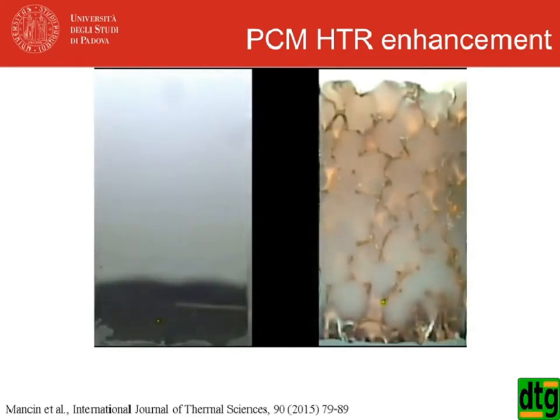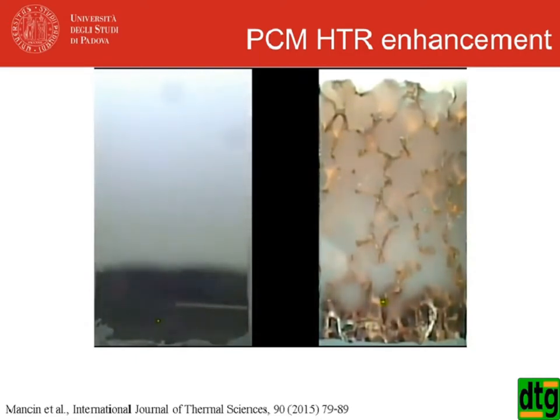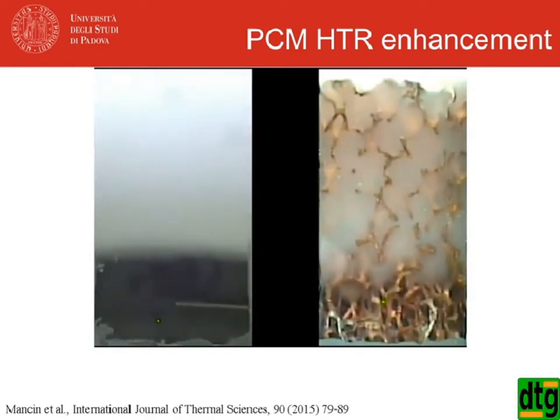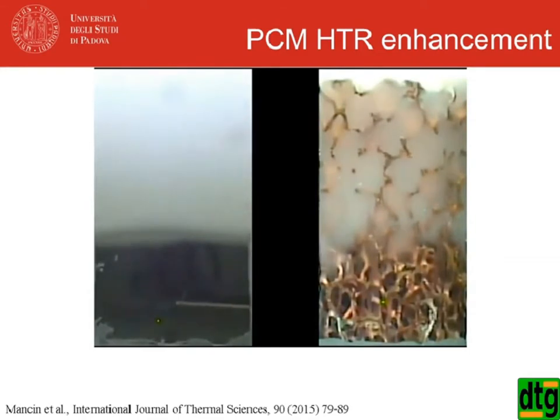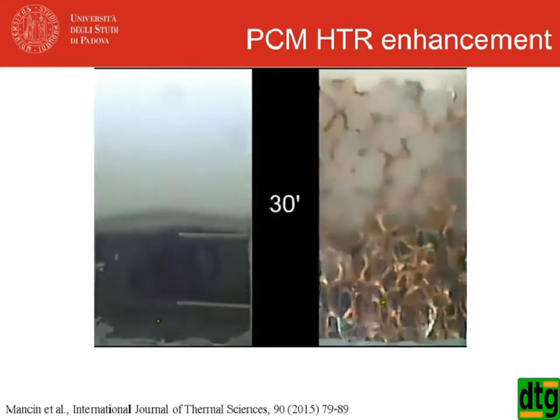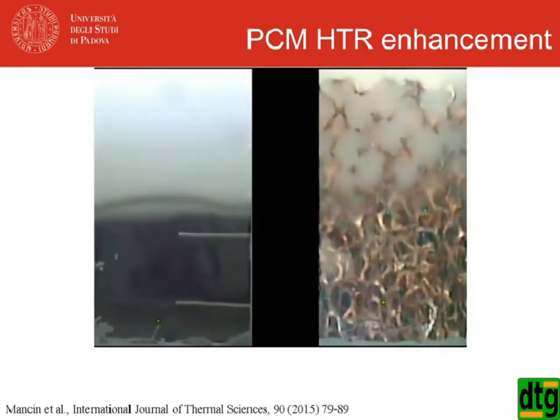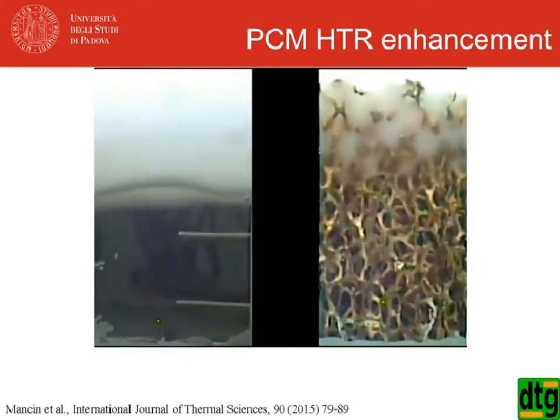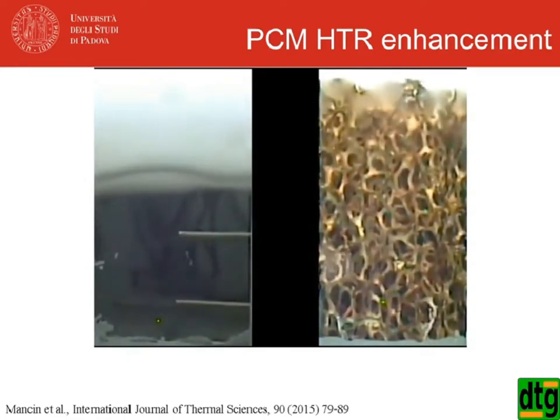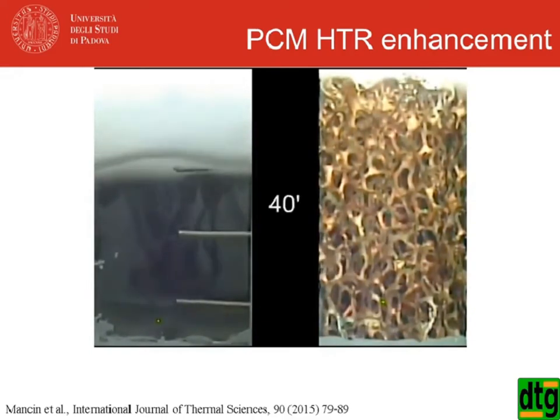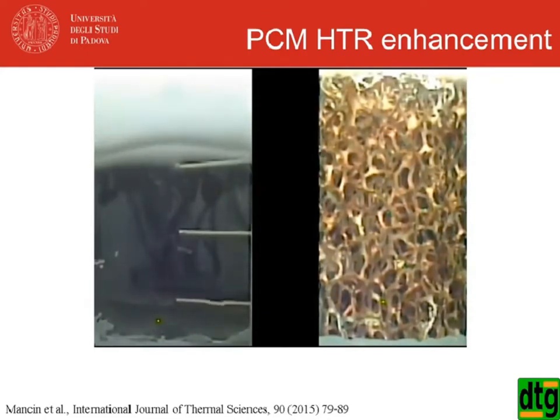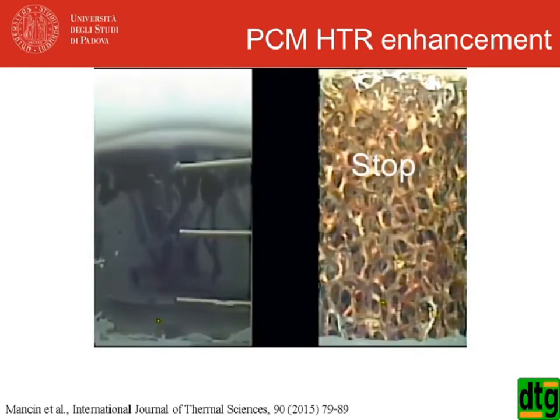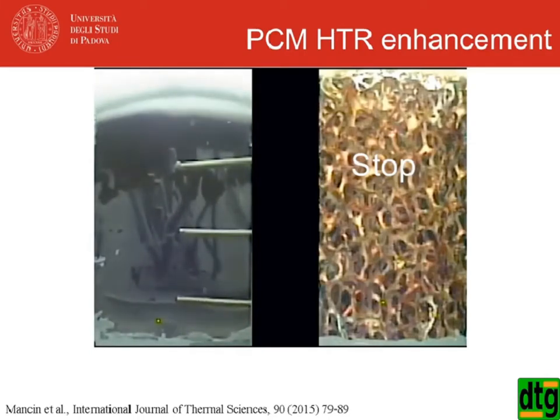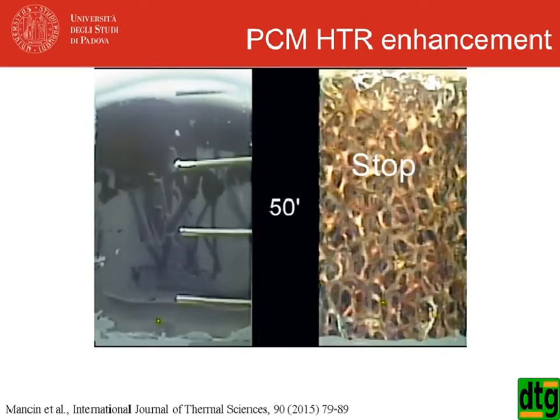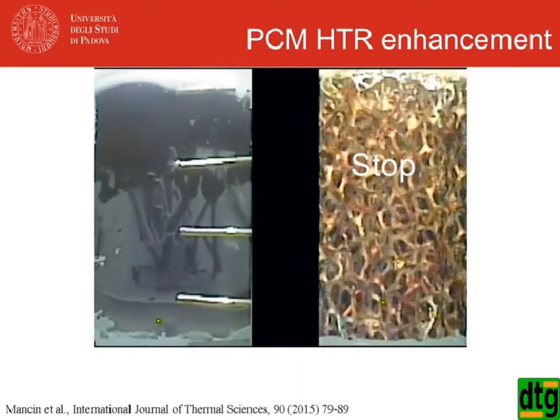After 20 minutes, something started also in the system with foam, and the phase change proceeded very fast. In fact, you see here at 30 minutes, the phase change in the box with the foam reached and overcame the process on the box without any foam. And after 40 minutes, basically the phase change was complete in the system with foam, while on the other system, only 60%, let's say, of the entire PCM was melted. And if you see here, I'm sorry for the low quality of the video, you see also the convection occurring in the system without foam, which was completely suppressed in the system with the foam.